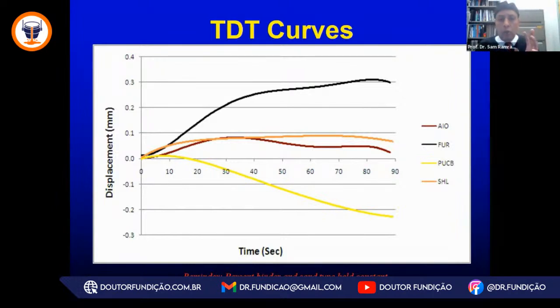These systems, they all show a different shape, and you can see an undulation pattern indicating that there is different thermomechanical, different thermal chemical experiences for these binders. And the thermal distortion curves are almost a signature for the sand binder levels that we are using for a sand type. Certainly, some of this distortion is due to the fact that we are using silica sand, which has a purely expansion type of movement. The expansion is simply the cookie moving away from the hot surface. The plastic movement, when the binder system goes below the origin or when the curves sag down, is the cookie sagging around the hot surface of the test apparatus.